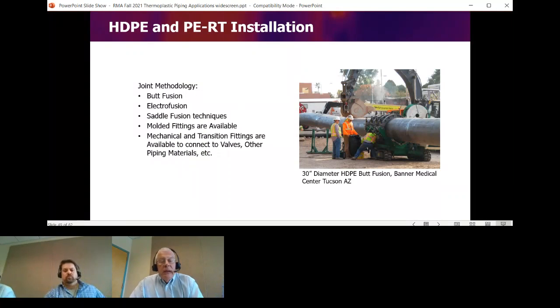As with the other pipes that Doug talked about, there are a number of connections. Fully butt welded actually takes one section of pipe to the other. You can see on the right, they are doing a joint in which you plane the ends so you have a uniform face around the connection, heat it up, and then pressure bond it together. But there's also electrofusion, which has electrodes in the couplings, etc. There are some saddle fusion techniques. Molded fittings are available, but typically under 12 inches. When you get into larger fittings, they're often shop manufactured and of the same DR or maybe one DR larger.